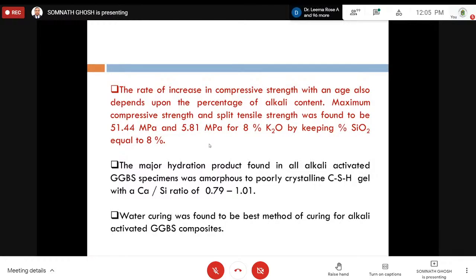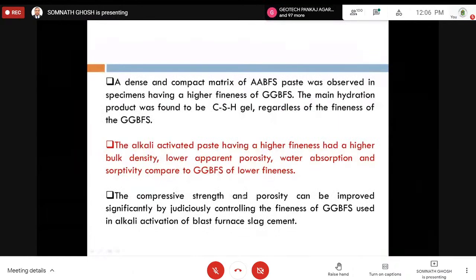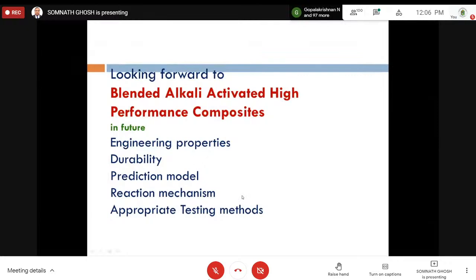So these things, tensile strength. Then regarding calcium silica ratio, because calcium quantity is very high in such slag. And water curing we have found. Right? So these are the different things. So I'm really looking forward to blended alkali activated high performance composites. We have worked a lot in blended alkali activated high performance composite with 6 different types of source materials combined together in different proportion and activated in different way, and particle sizes, differing temperature, many things we have changed, and you produce admixed blended alkali activated high performance composite.